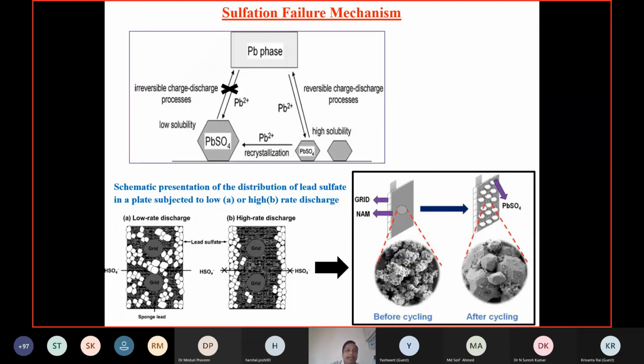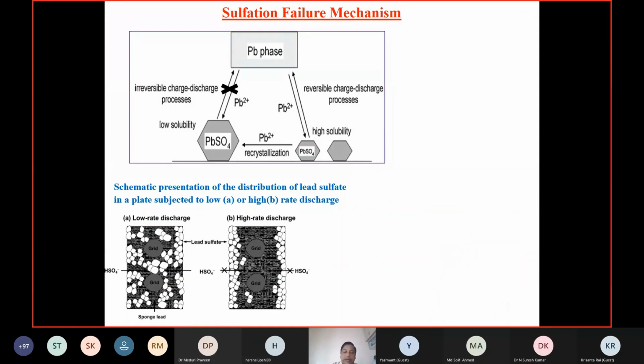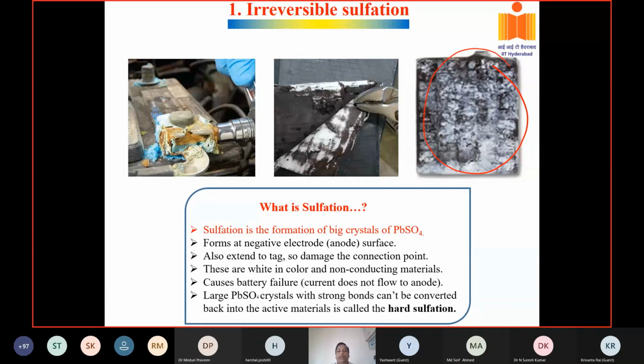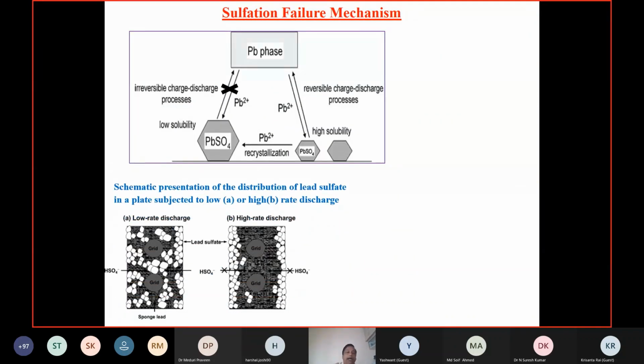Another thing that happens: at slow rates, like C/20 rate, a 20-hour or 10-hour charge-discharge, you have enough time for the electrons to move and ions to flow. But what happens when you go at high rates of charge, like 1C or 10C? You have sulfate on the surface. It doesn't allow the sulfate ions to move or electrons to flow, because they cannot go into the interior of the plate in the small time. So the performance becomes zero. Suppose you are using it for an electric vehicle application: it is not going to work at high rates, like when you put the brake, not going to work at all. This is called high rate partial state of charge, HRPSoC.